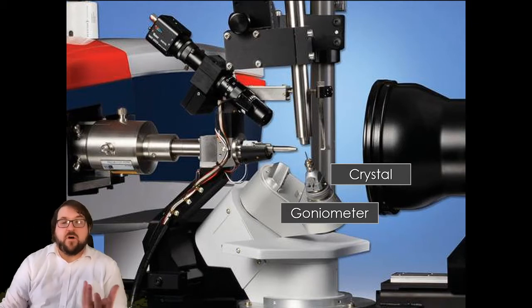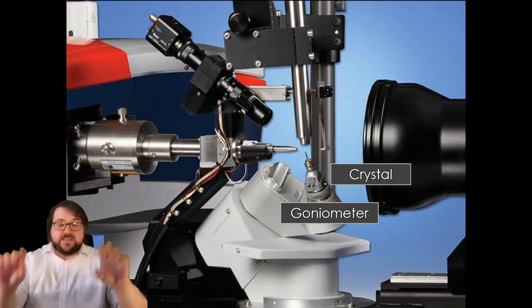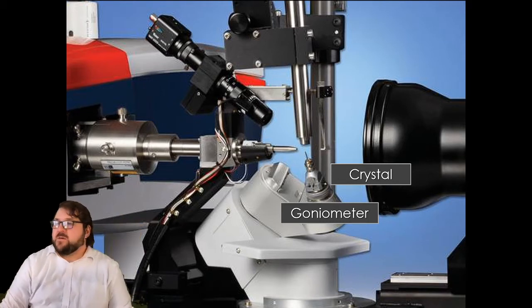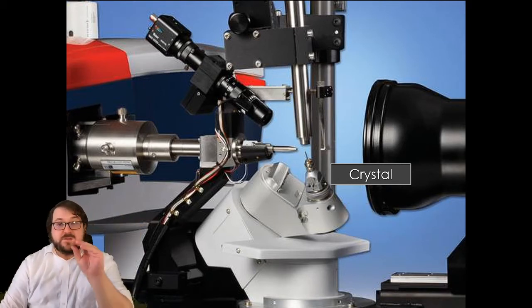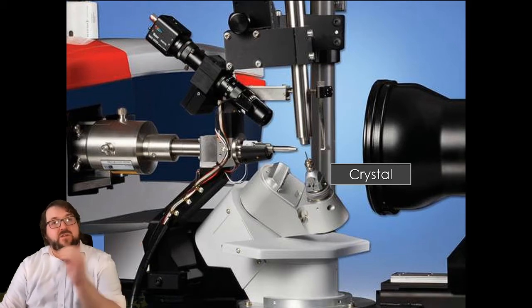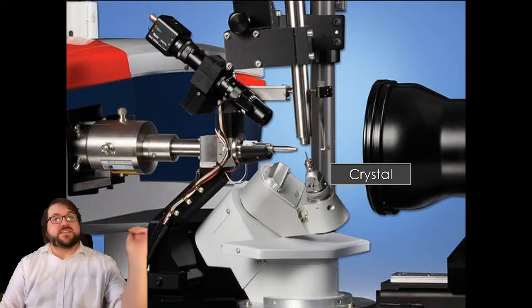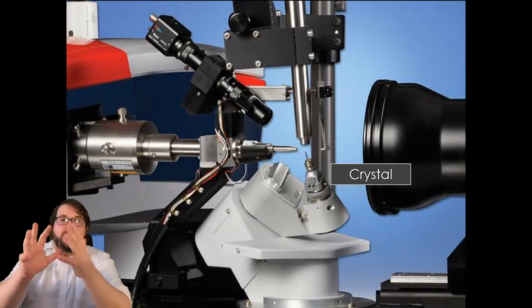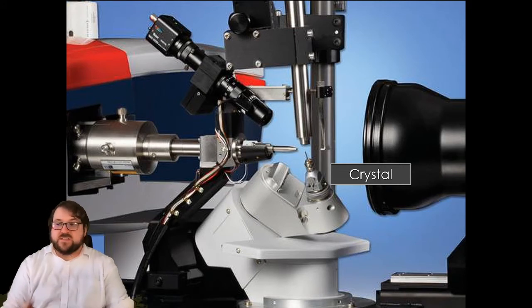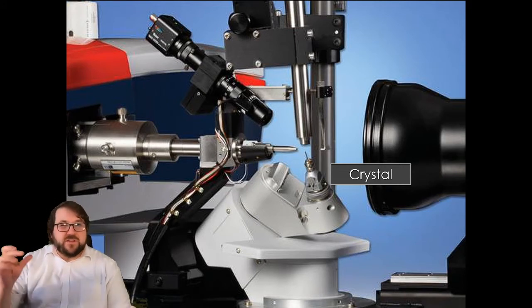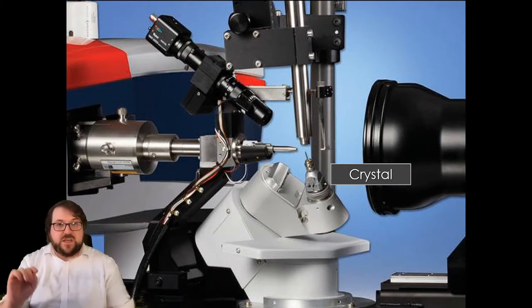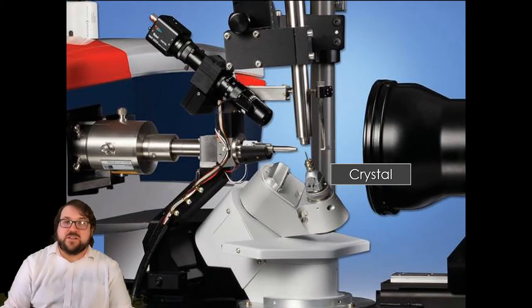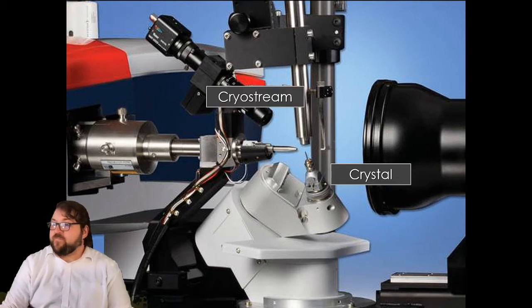Now I mentioned before that we're taking 2D images of the X-rays coming through. But what we then do is we turn the crystal half a degree and we take another image, and then we turn the crystal half a degree and take another image. And we look at how that image changes as we move that crystal around. That means that rotation, we can sort of use that as a third dimension. We've already got a 2D image, but now we've got a third dimension that we can start to change.